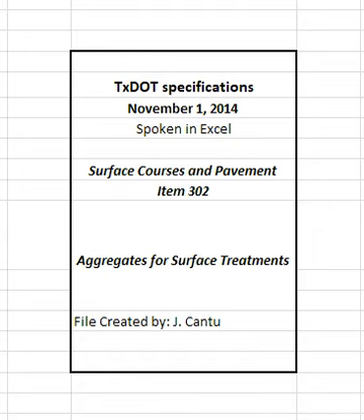4. Construction. Deliver aggregate to the locations shown on the plans. Prevent segregation, mixing of the various materials or sizes, and contamination with foreign materials when aggregates are stockpiled. The engineer will reject contaminated stockpiles. Provide adequate initial cooling of precoat aggregate to prevent asphalt or aggregate damage due to excessive heat buildup in stockpiles. Limit stockpile height to 3 feet immediately after production when asphalt cement is the precoating material. Consolidate stockpiles after adequate cooling, as approved. The engineer will reject stockpiles showing evidence of damage due to excessive heat buildup.